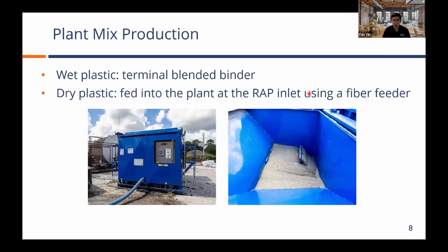Nathan showed a quick picture earlier in his PowerPoint of the feeder system that we use to add the dry plastic pellets during production. It went really well. We fed into the plant at the RAP inlet, and then we verified the dosage. It was very accurate compared to what we were targeting. So we were very pleased with that.